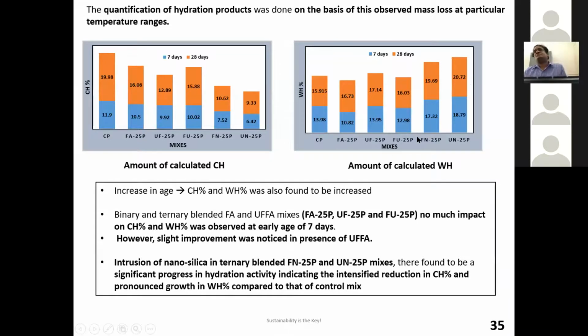Now, what is DTG? Well, we know DTG is the water associated with the hydration process, or an indirect measurement of calcium silicate hydrates. So do you need more CSH or not as a civil engineer? Well, of course, you will say yes. As a civil engineer, I need only calcium silicate hydrate. That is what defines the engineering properties of the concrete, of the cementitious composite. So you can see here, the moment I'm going to the blend with nanoparticles, the calcium silicate hydrate formation is much more as compared to the control, the fly ash and binary blended mixes. And that is what nanosilica can do if you can handle it.